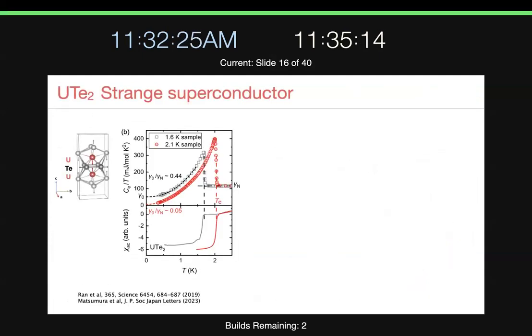Okay, let me just go on and look at my other motivation, which is this crazy guy. This is uranium ditelluride, which is a strange superconductor. At first sight, it looks like a perfectly average heavy fermion superconductor. It's got f electrons on the uranium sites, and it goes superconducting. In the early samples, it went superconducting at 1.5 Kelvin, and then they discovered a nice way of making this in molten salt, and the Tc went up to 2 Kelvin.